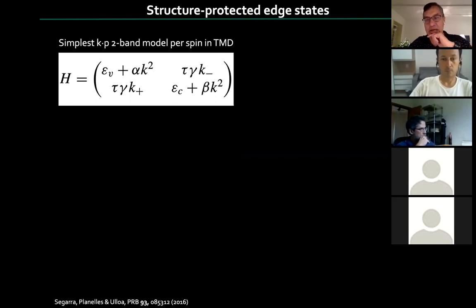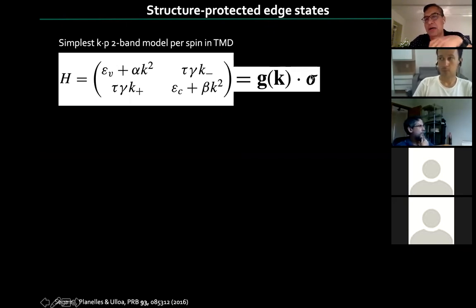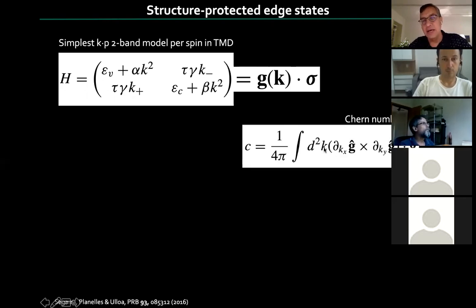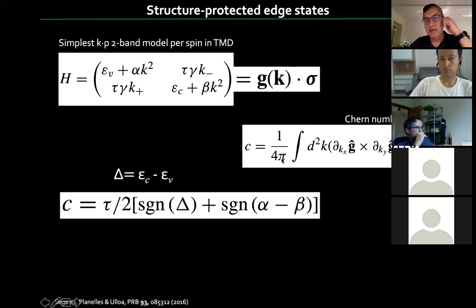Now, what is nice about a Hamiltonian like that is that it can also be written in terms of the Pauli spin matrices times this vector. And so this immediately gives you this connection with the geometry of the k space. So by looking at this effective Hamiltonian that has a structure in reciprocal space, you can extract that structure by looking at the Chern number, for example, which is the Berry curvature integrated over the Brillouin zone. And this tells you whether the geometry is interesting or not. And it turns out that you can do this analytically. I mean, it's simple enough that you can do this analytically. And the Chern number is given by this expression, where delta here refers to the band gap, right? And alpha and beta correspond to these coefficients that give you the local curvature or the inverse effective masses, or whatever you want to say.